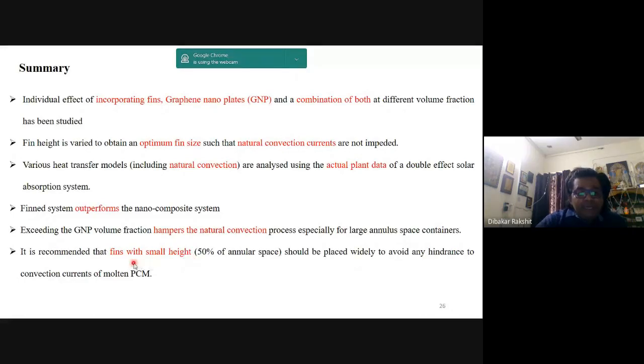And as I told, the optimum fin height was found to be 50% of the annulus, and that was what we envisaged from utilization of this type of structure for designing our thermal battery. So you can see that this holistically gives the utilization of the fins and the graphene nanoplates in combination with each other to find the optimum fin size, which is around 50% of the annular size, so that the natural convection is also not getting inhibited by increasing the fin height. And of course, if we are increasing the fin height beyond 3/4 of the R minus r, then those fins actually start acting as heat sources, which is also not a very good thing.